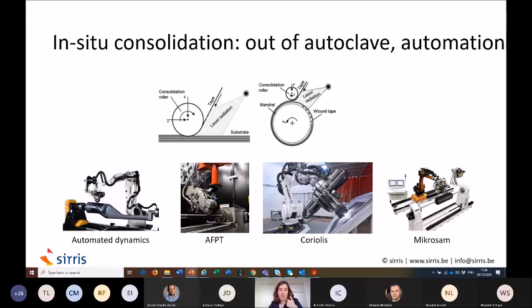Going even one step further, you can not only spot weld, as we saw in the previous slide, where you just weld the tapes on top of each other at specific spots, but you can also use a continuous process. That means that you very locally weld the tape on the previous stack, and you can do that for a flat structure, you can do that for wound structures.